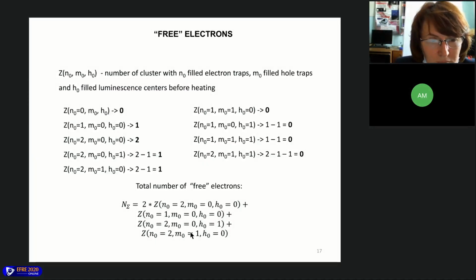According to our previous analytical estimations, let us show the expression for left electrons. As in the previous case, we take into account the strong influence of localized recombinations. Thus, each cluster which contains electrons and holes invests fewer electrons than a cluster which contains electrons only. For example, clusters with 2 electrons, one occupied luminescence center and one occupied deep trap, invest no electrons since they will recombine with holes during heating in the low temperature region. The expression for left electrons is given below.